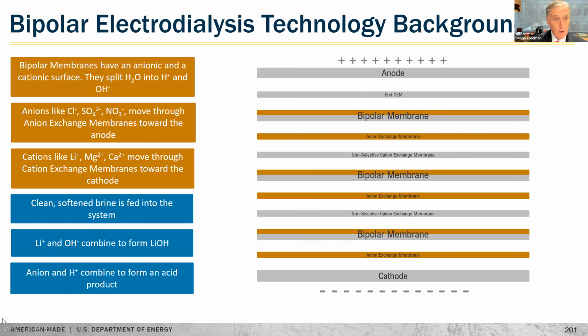And so bipolar electrodialysis, as it's practiced conventionally, has 3 types of membranes in it. It has a bipolar membrane that has a positive side and a negative side. And this takes water and makes H+ and OH-. So this is where we get the hydroxide for lithium hydroxide. It has anion and cation exchange membranes to help separate the other ions based upon charge.